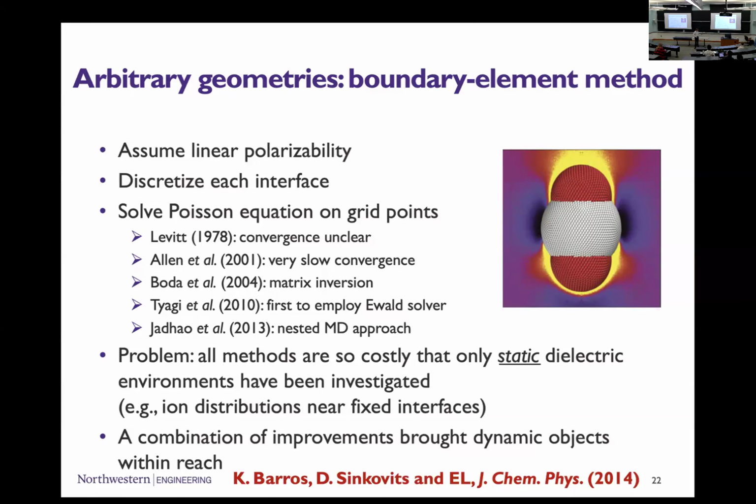Oh my God. So now the silica is charged. Unless you're at the isoelectric point, the silica will be charged. There are ions around, so there's a very complicated electric field. There's an external electric field. Every interface between any material will be polarized, right? So this is the silica with water, it's the silica with this polymer. And then the electric field itself, of course, is complicated because these ions are also responding to the external electric field. And now you say, okay, do you have a lot of these particles and they form a complicated structure? Please explain. That's, of course, extremely complicated.